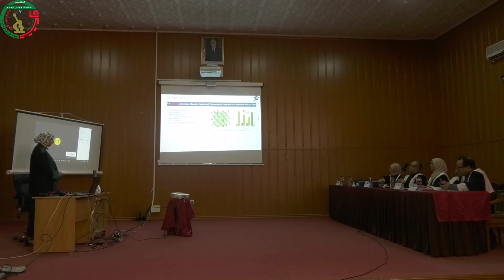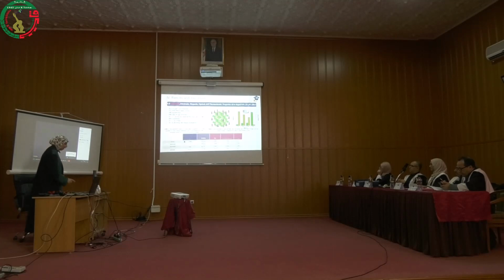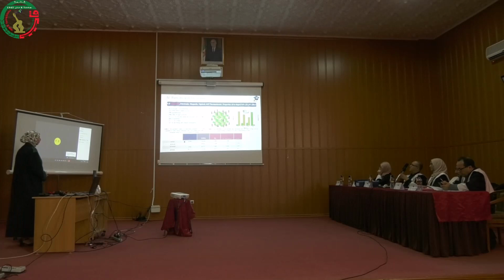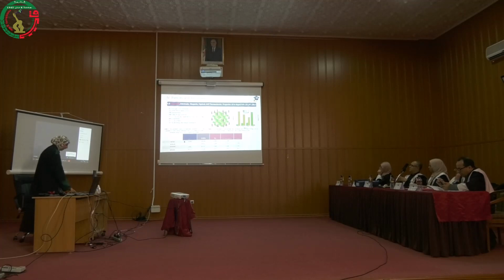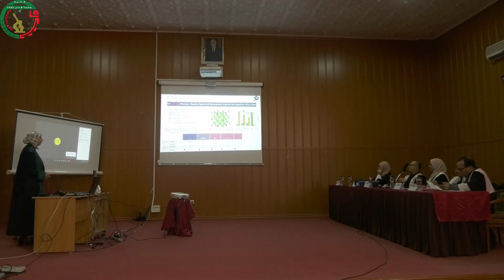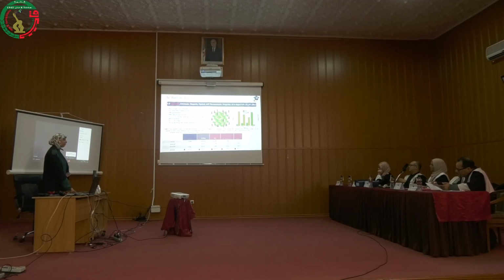An illustration of the cubic structure and the total energy and cell volume for the co-doped compounds are given in figure 5, and the results are tabulated in table 4, in which it is evident that compared to the monodoped compounds, there is an increase in the lattice parameter and a decrease in the bulk modulus. The formation energies are also negative, indicating their thermodynamic stability. The energy differences are positive, indicating the stability of the ferromagnetic state, and the Curie temperatures are also found higher than room temperature, indicating their suitability for spintronic applications.